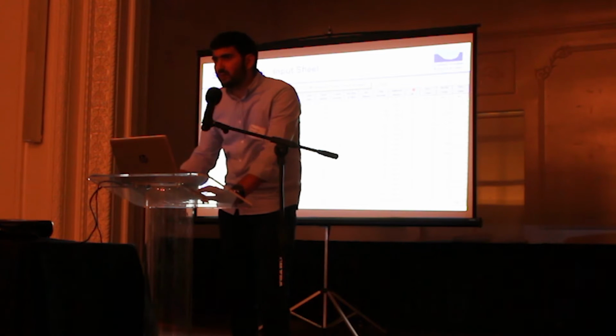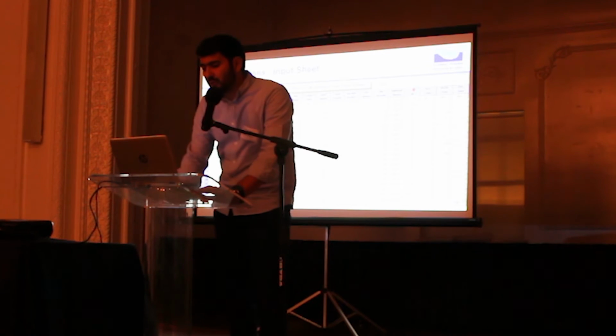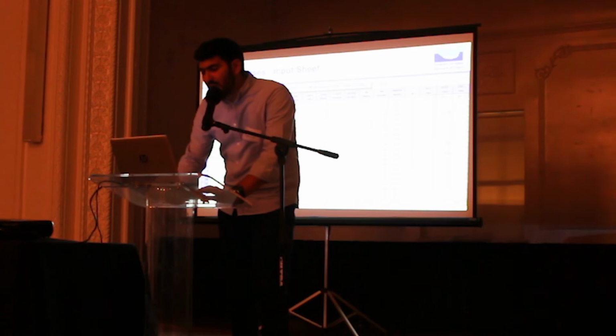And a good feature about this model is that even if we don't have the pH entered in the input screen, this model can calculate the pH for us based on the CO2 partial pressure and the bicarbonate that is initially added into the system. All right. So here I have a couple of cases, for low temperature and high temperature cases.